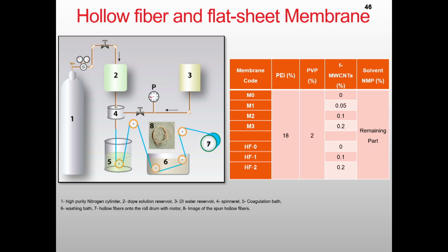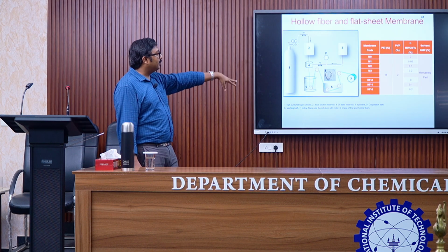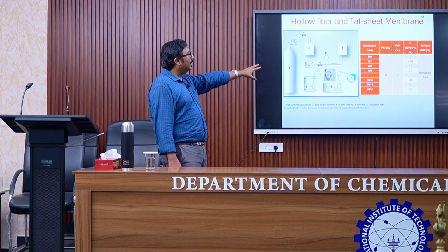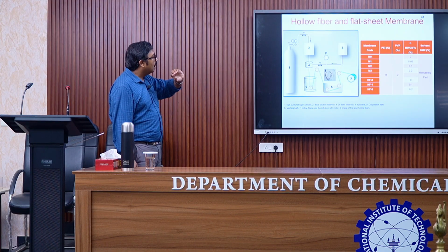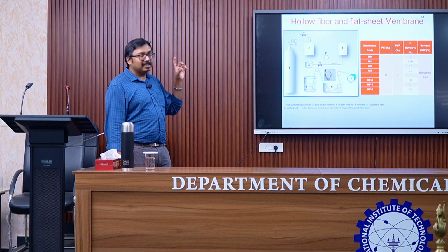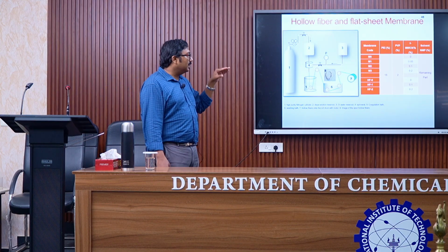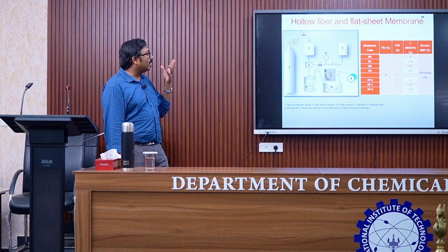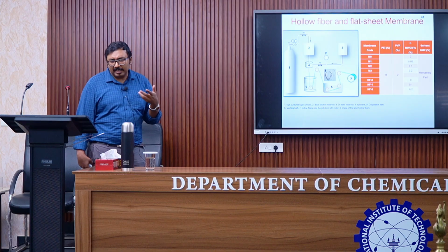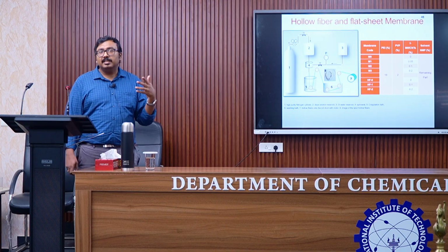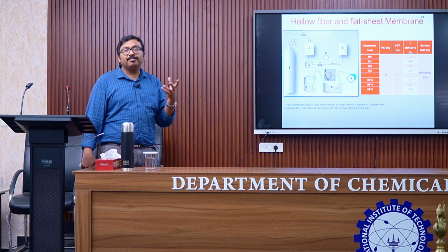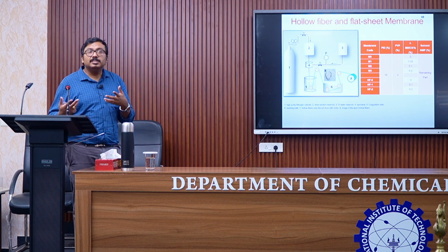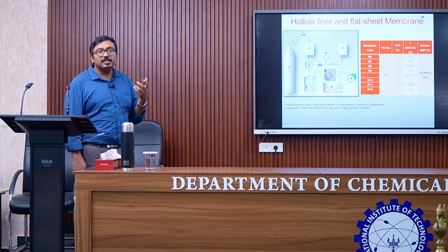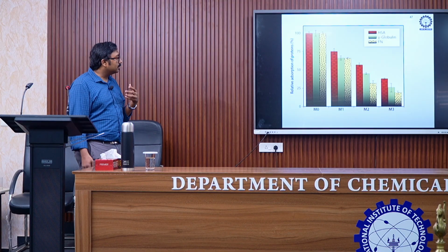These were the HR-TEM images of these. And this is how we made both flat sheet as well as hollow fiber membranes in this case. The ones that have an HF notation stand for the hollow fibers, and the ones that are M0, M1, M2, M3 are all flat sheet. We used polyether imide membranes again with the same plasticizer and varying concentrations of the functionalized multi-wall carbon nanotubes. Carbon nanotubes inherently have only carbon, and unless they are oxidized, they don't have any functional groups. Once they are oxidized, they have oxygen functional groups, OH or COOH. That again makes them hydrophilic and able to disperse into the polymer matrix.